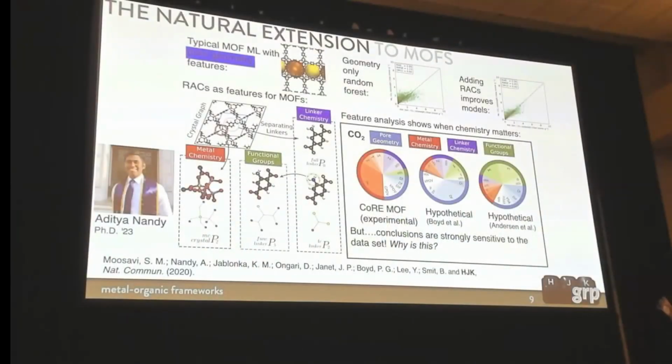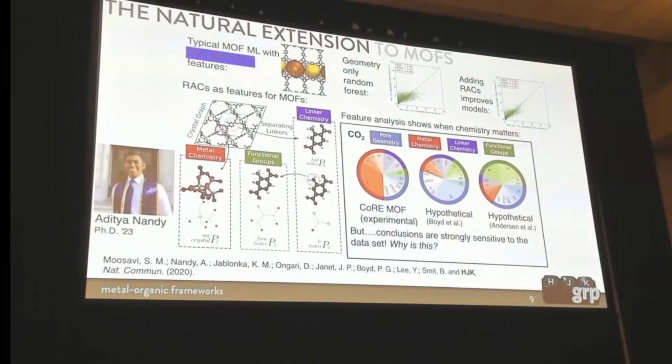If we get it from an experimental set of models, which is a data set of around 10,000 MOFs that have been experimentally crystallized, and we compare a model trained on the experimental data versus a hypothetical data set, we see much more metal chemistry coming out when we train on the experimental set. These are still simulated results, but whether they come from a set of experimentally characterized MOFs or ones that have been hypothetically enumerated leads to vastly different conclusions. This is troubling because it suggests that our design rules may depend on the data set we start with.